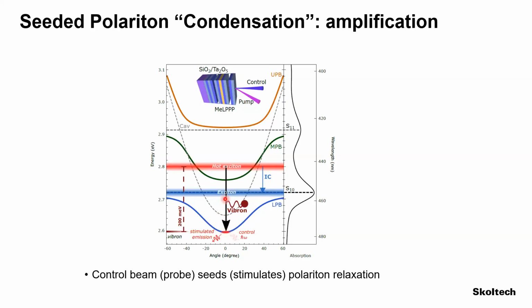And now having this very low threshold polariton condensate, we thought of actually trying to see if we can stimulate, if we can seed the condensation. So if we pump optically hot excitons just below the condensation threshold, and then we bring a control beam, which is resonant to the ground state. This is similar to the concept of a laser. We put one polariton at the ground polariton state, so we create occupancy of one, and then all polaritons in the structure, they come and they coalesce at the ground state. So we create polariton amplification. It's not condensation anymore because there is no thermalization, but it is polariton amplification here.